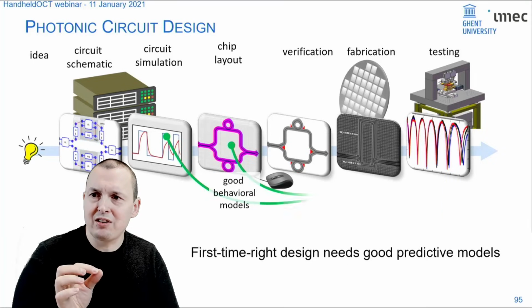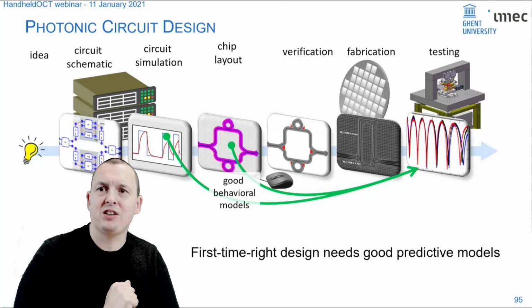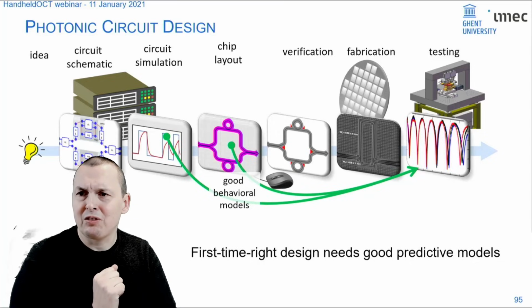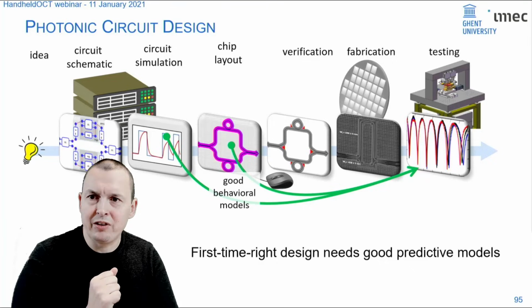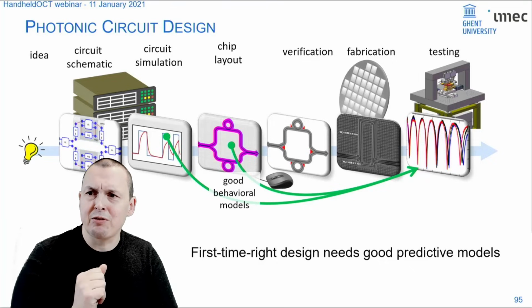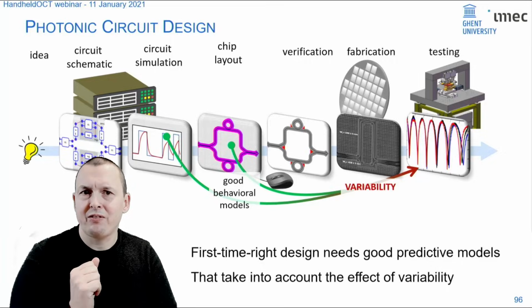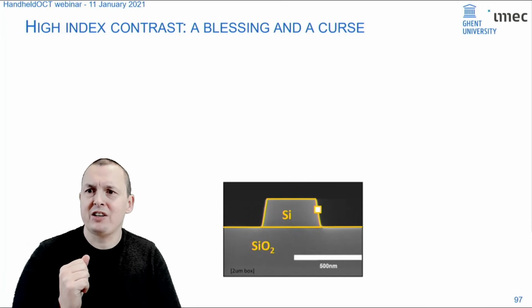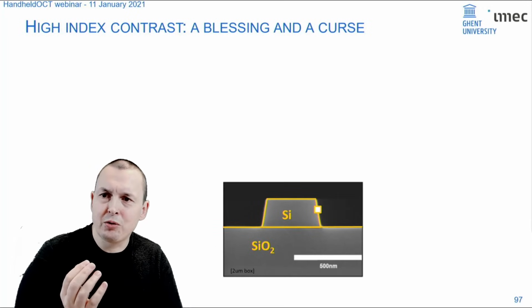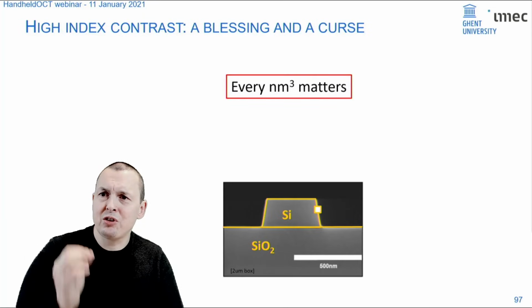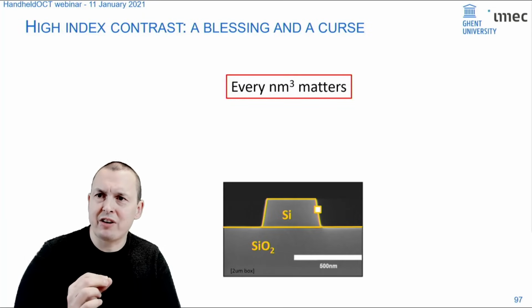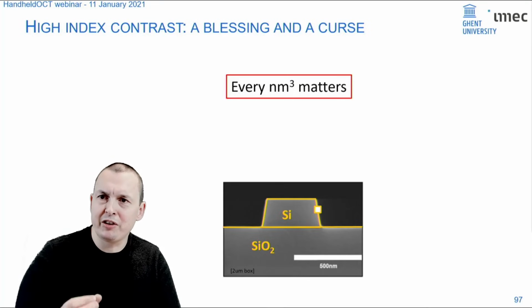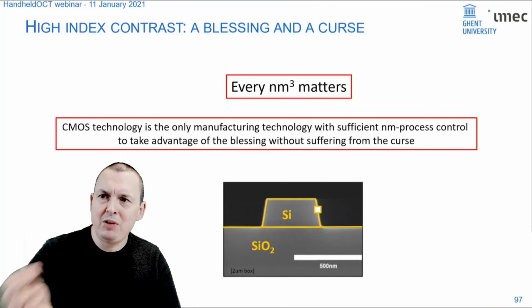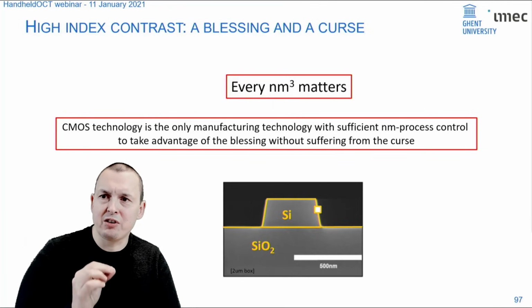You need something that allows you to predict in advance what is going to happen after you have fabricated your circuit. The difficulty in this kind of predictive capability is variability. These silicon waveguides that I showed before, they are only like a few hundred nanometers across, but they're so sensitive to even nanometer scale variations. The high index contrast means that if you remove a cubic nanometer of material, you will already be able to observe it. That means that you need really, really good process technology, and even then, you will be suffering.